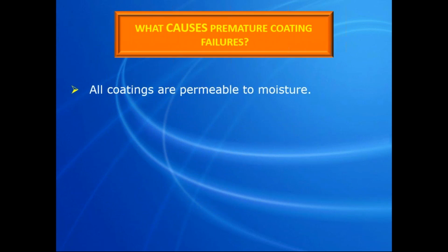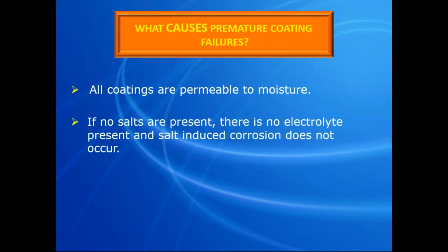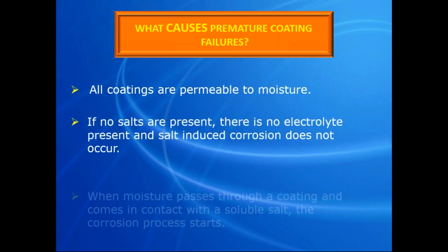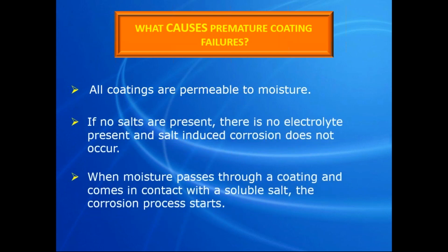All coatings today are permeable to moisture. If no salts are present, there's no electrolyte present, and salt-induced corrosion does not occur. When moisture passes through a coating and comes in contact with a soluble salt, the corrosion process starts.